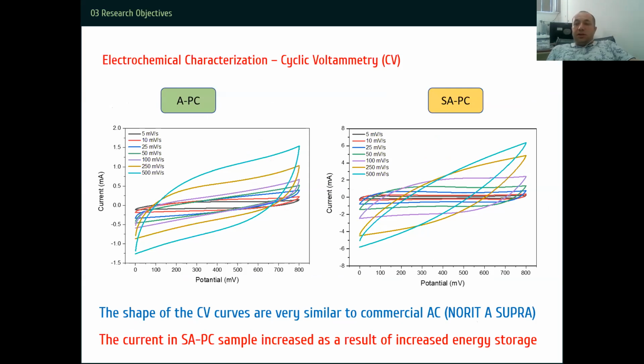When we check the cyclic voltammetry CV analysis, first of all, as you see, the shape of the CV curves are very similar to the commercial activated carbon, Norit A Supra, and the current in the SAPC sample increased as a result of the increased stored energy. You can see from the graphs, this is 2 milliamps, and in SAPC sample, we have almost 7 milliamps, as you see.